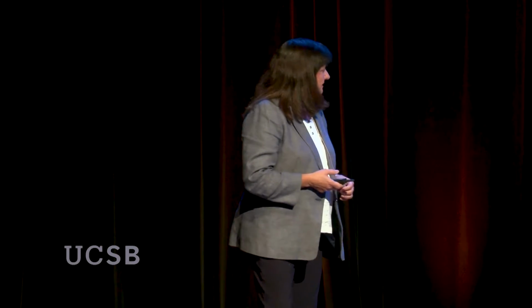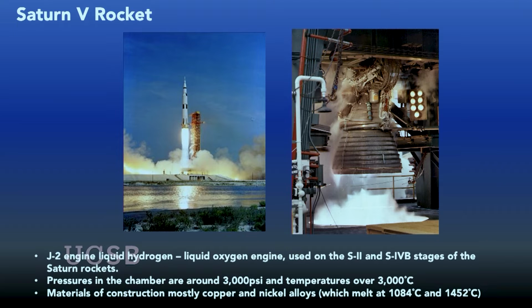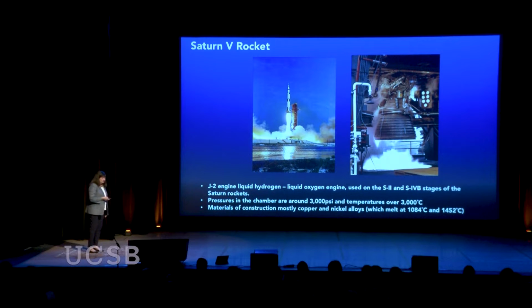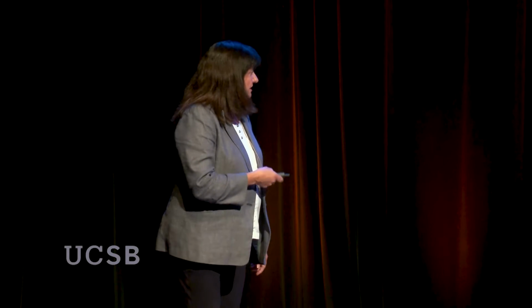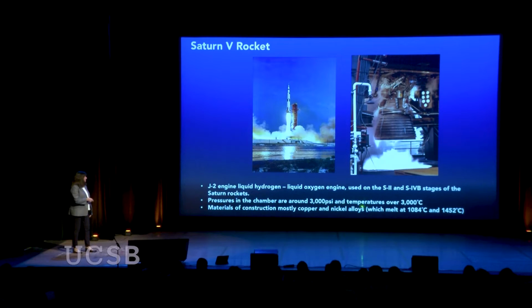Okay, the Saturn V rocket. I want to talk a little bit about both because they are different. Rockets are often fueled by a combination of liquid hydrogen and liquid oxygen. This is the rocket that took the astronauts to the moon, and this is a close-up of the nozzle that's producing all of this lift. Just to give you some sense of the environment, in here we have pressures of about 3,000 psi and temperatures over 3,000 degrees C. Now this nozzle is mostly composed of copper and nickel alloys, which melt at 1084 and 1452 degrees C, respectively.